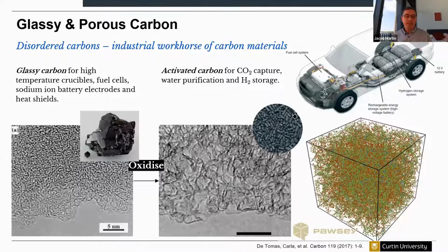And why are they so interesting? Well, they're really the industrial workhorse of the carbon material world. So in terms of the higher density materials, these hard carbons, they can be used as crucibles, heat shields. They're used in sodium-ion batteries, fuel cells, and also as electrodes in electrochemistry. If you oxidize those materials, you produce a lower density material with a lot of porosity. And these are activated or nanoporous carbons, and they're used for water purification and then capture of gases and hydrogen storage. Here's a hydrogen fuel cell car, and the idea here is that you would cool down the activated carbon to liquid nitrogen temperatures and allow the hydrogen to be stored at a lower pressure.